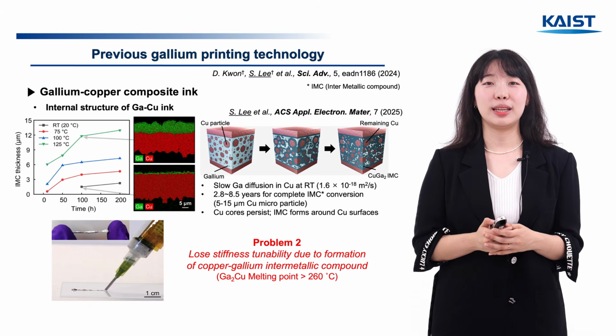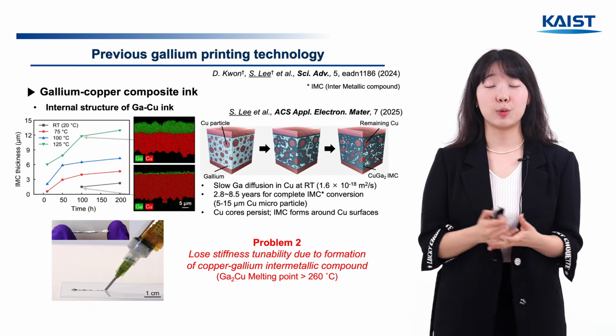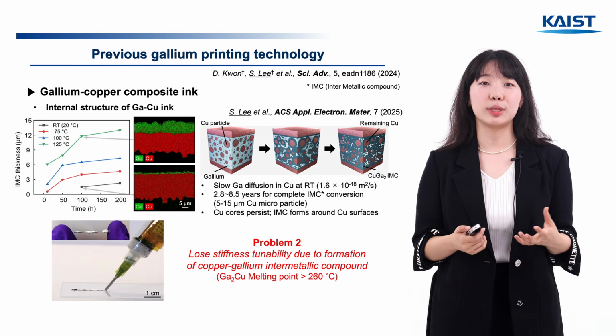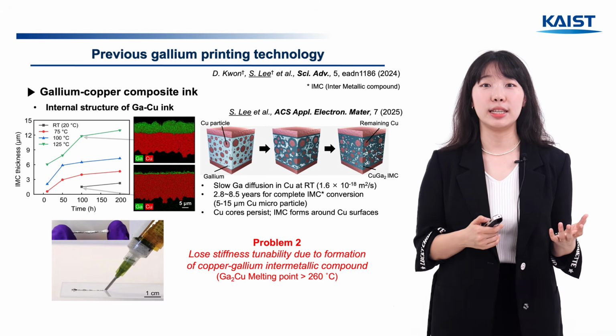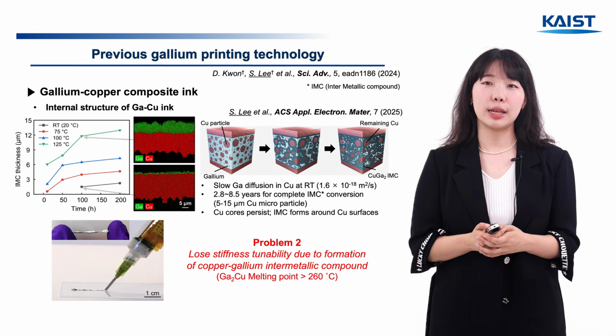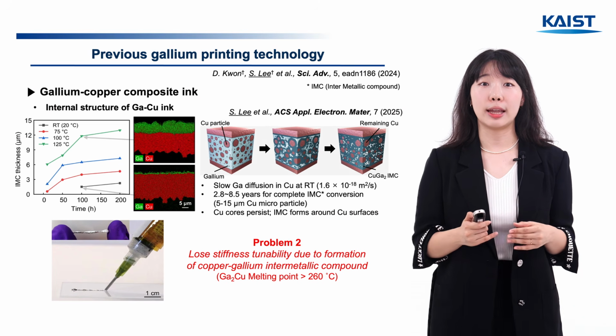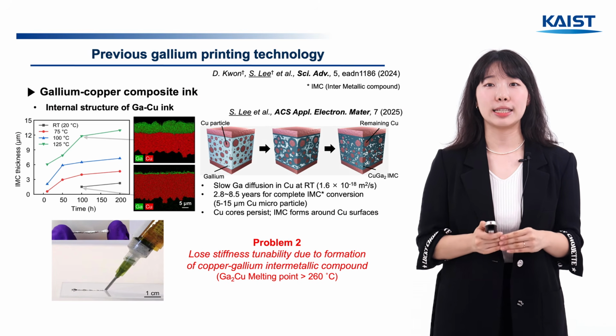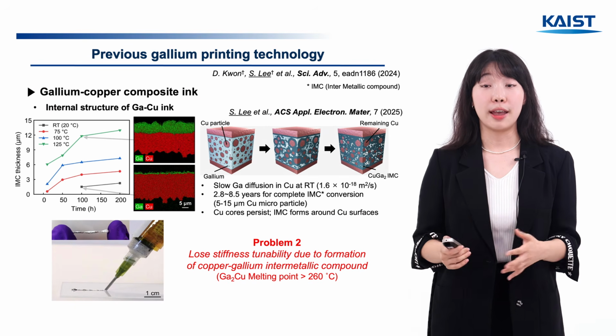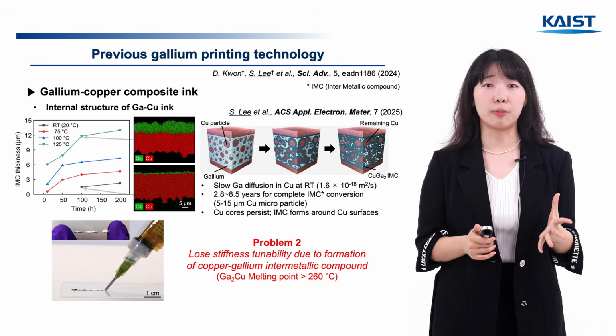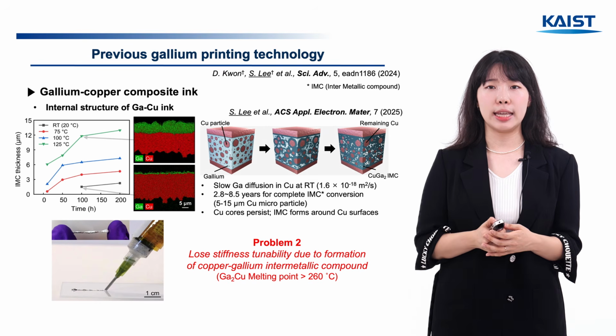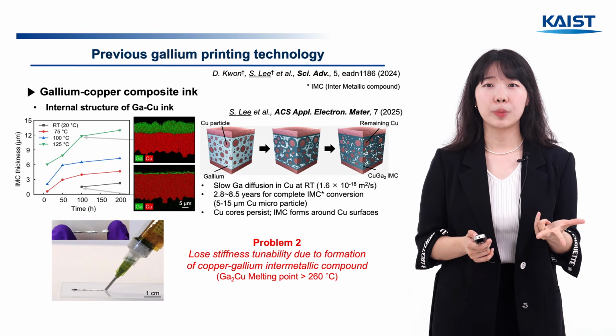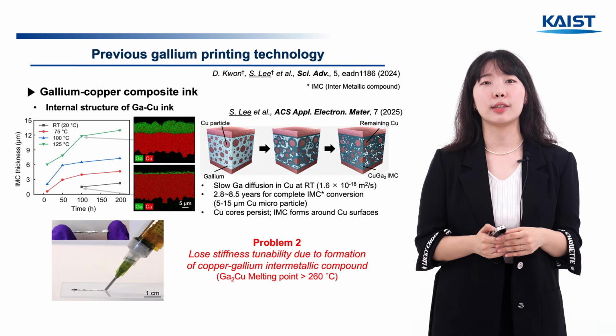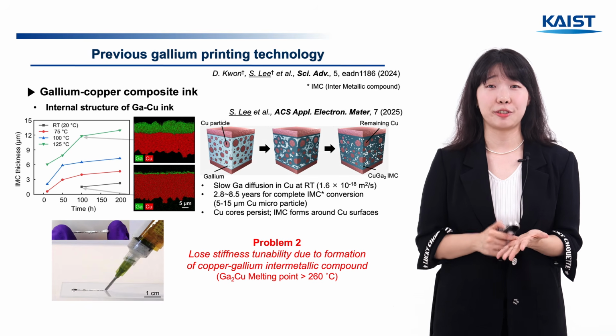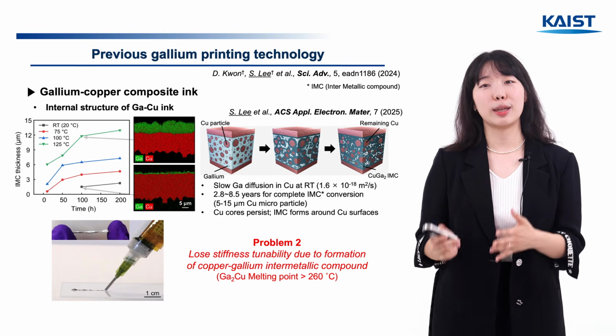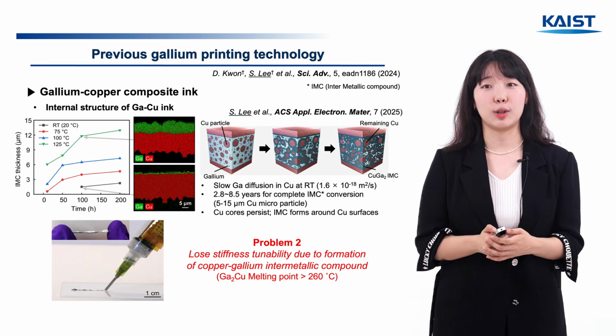The second problem is that when gallium stays in contact with copper, it forms an intermetallic compound, or IMC in short. So in this paper, I measured the diffusion speed, and based on that, you can calculate how fast gallium diffuses into copper. And for 5 micrometer of copper, it fully converts to IMC after about 3 years. Since this compound has a melting point above 260 degrees Celsius, once it turns into IMC, it loses its stiffness-tunable property.